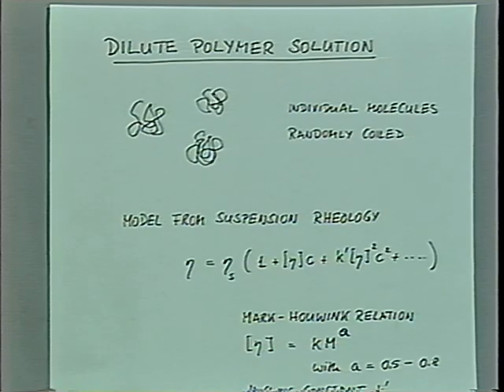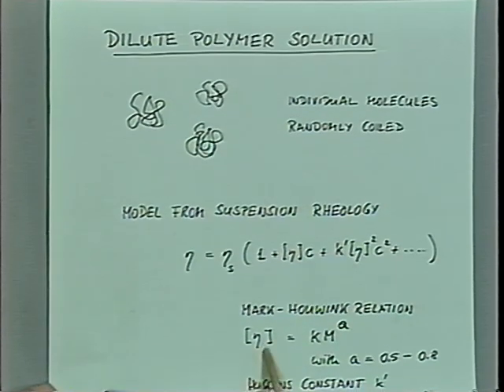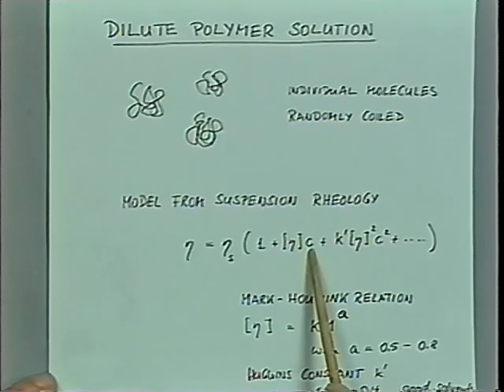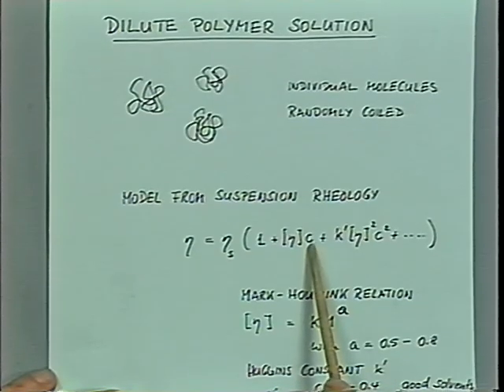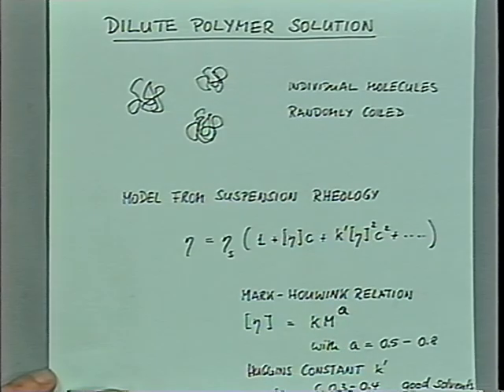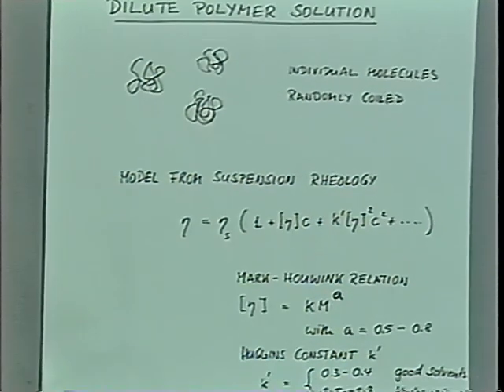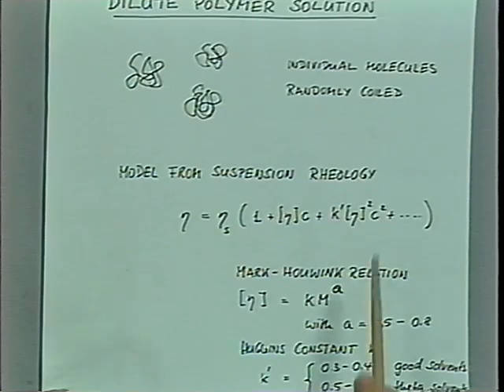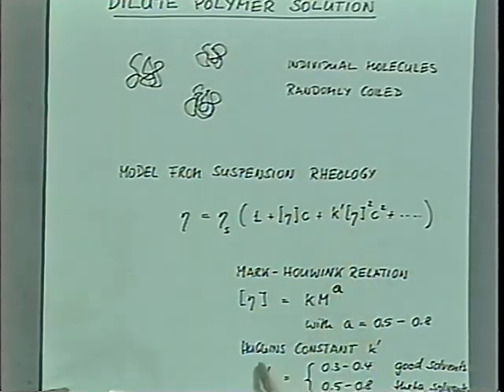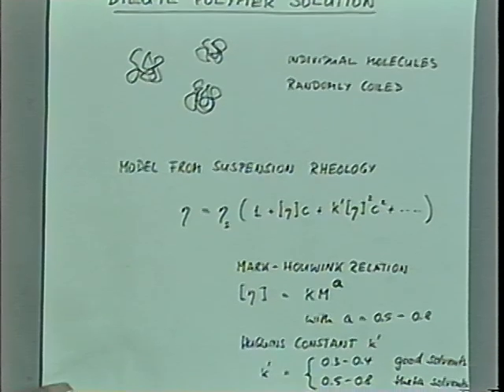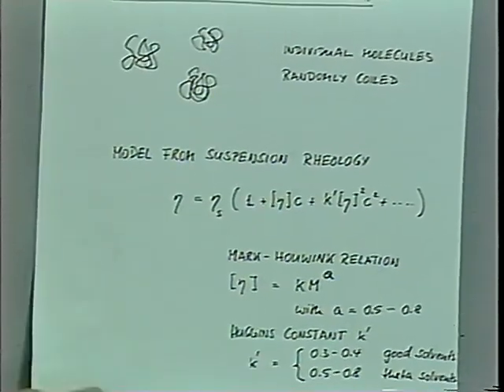So this is the intrinsic viscosity. It has the dimensions of one over the concentration, because this is a dimensionless term. So it doesn't have the dimension of poise. Now, for the nonlinear term here, the Huggins constant is on the order of 0.3 to 0.4 in good solvents, or theta solvents, 0.5 to 0.8. And we have to talk about the solvents in a moment.